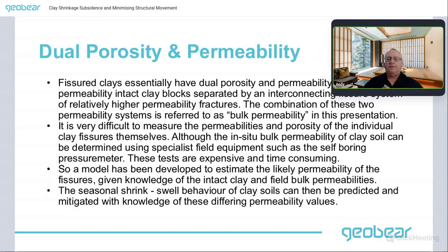There's an interesting fact about fissured clays. And this is really quite important in terms of why I think certain formations really show significant movement. Fissured clays essentially have a dual porosity and permeability, with low permeability intact clay blocks separated by an interconnecting fissure system of relatively higher permeability fractures or fissures. The combination of these two permeability systems is referred to as a bulk permeability in this presentation. So that is the combined permeability of both the intact clay and the fissuring system.